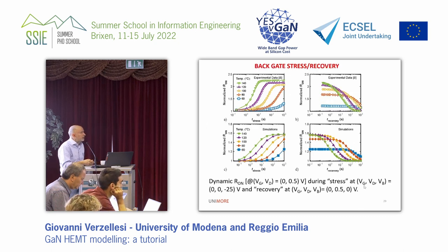And here we have experiments obtained by stressing the device in a different way, stressing the device by the back gate. These are the stressing conditions: 0 at the gate, 0 at the drain, and minus 25 volt to the backside. Very similar kinetics to our own, and quite interesting agreement obtained with simulations, also in this case.